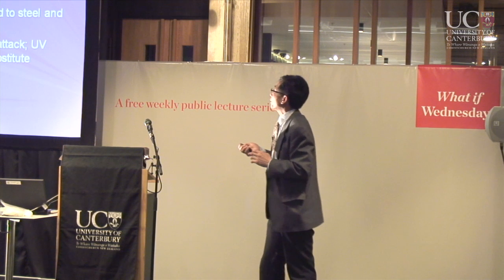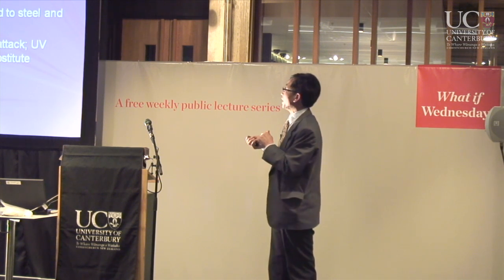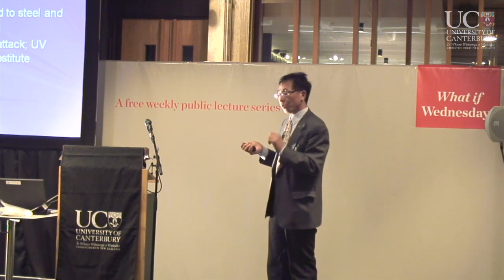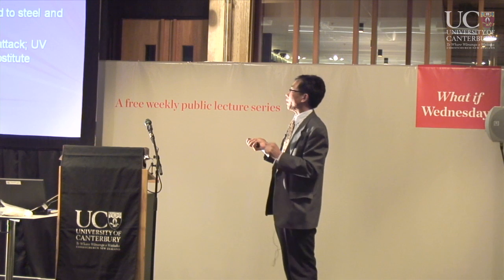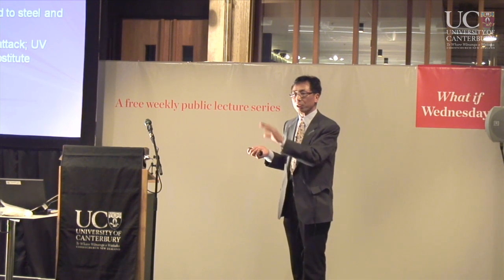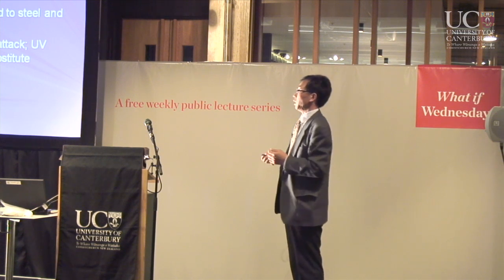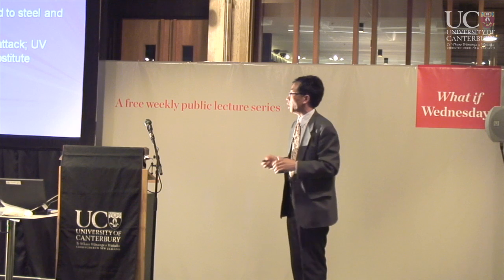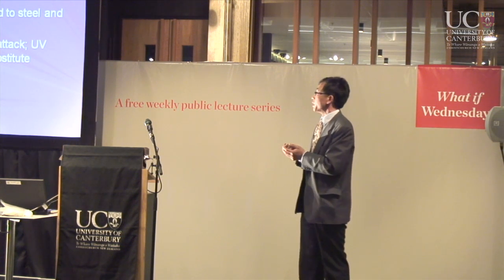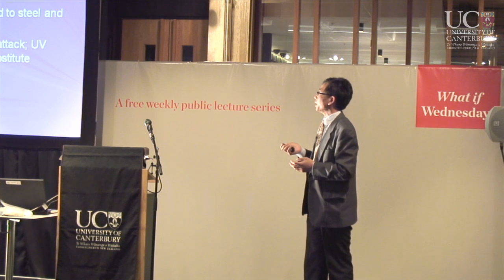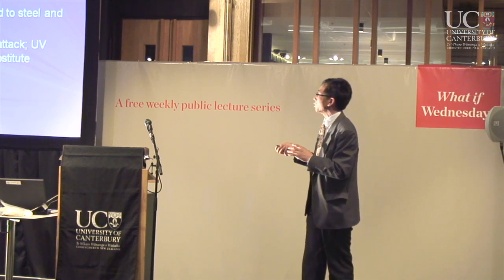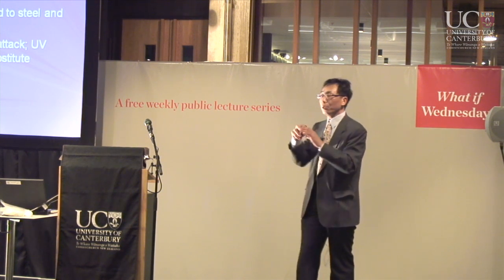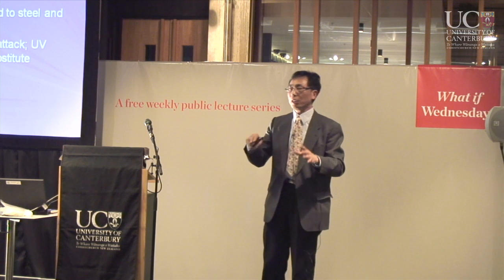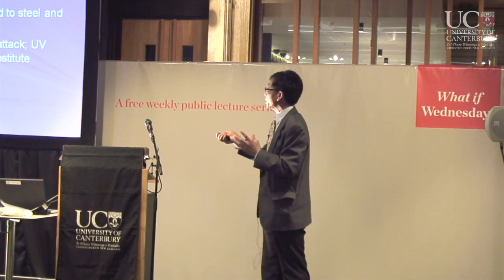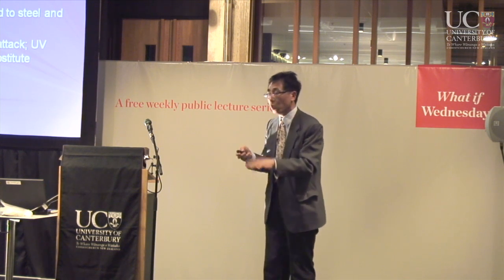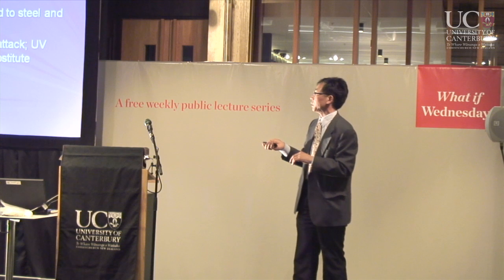Okay, so what are the key features of the wood plastic composite? The material is more stable compared to wood. If you put the material in water, it does not absorb much water and does not change much in terms of dimension. It has a lower processing temperature compared to steel and concrete. We use a normal 180 to 200 degrees C to process these materials, so much lower energy is needed.